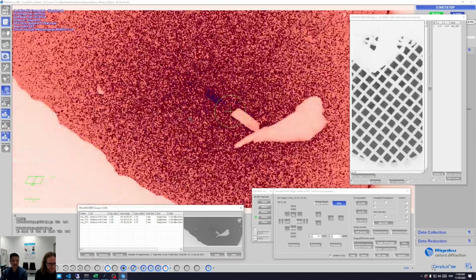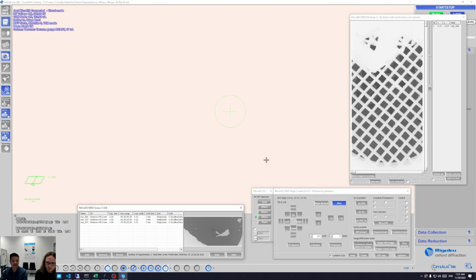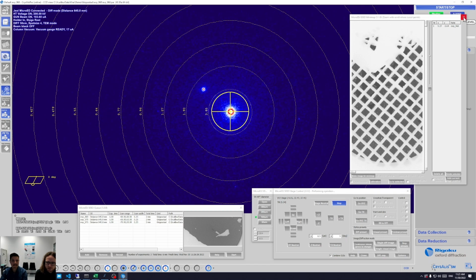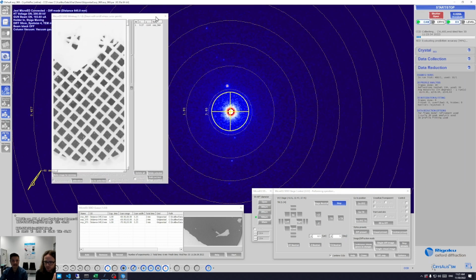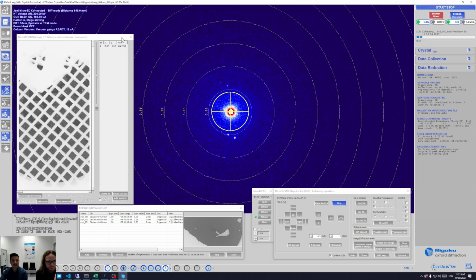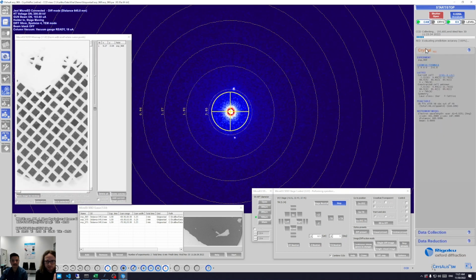And it will now, and this is actually quite an important feature, not only recall the position of the stage that we have stored before, but using image processing, it will take another visual image, and in case the grid should have drifted a bit, or the stage should have drifted a bit, which can happen, especially if you have a cryogenic sample where the holder over time can drift a bit in its length, it will realign the visual picture of your grain with what it remembered from when you initially selected it. This turned out to be quite an essential feature, and now it's working quite robustly.